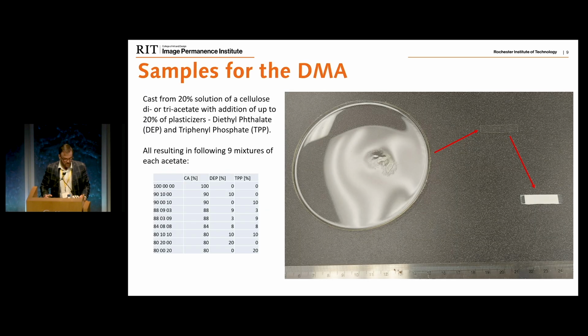So how are we preparing our samples? We, meaning my colleague Meredith, who's the chemist in our team. The samples are cast from 20% solution, and they are a mixture of either pure cellulose diacetate or triacetate with addition of up to 20% plasticizer. We are using two historically most popular plasticizers. And for each of the diacetate and triacetate mixtures, you can see here the composition.